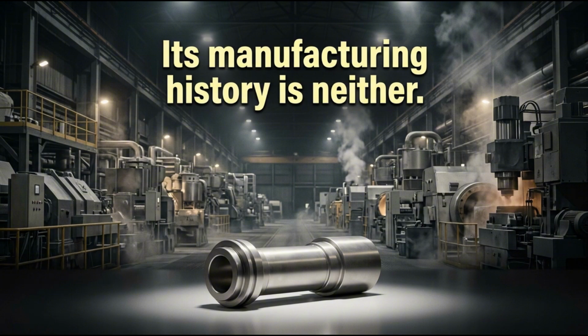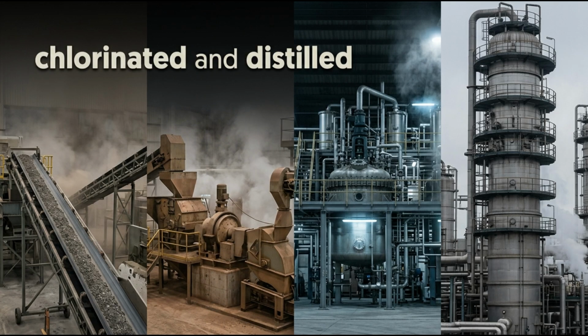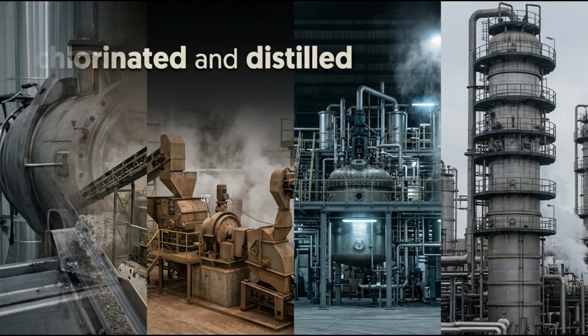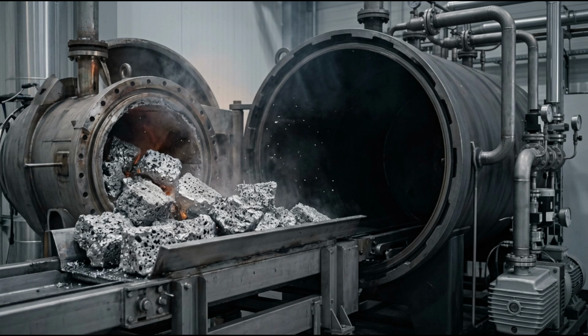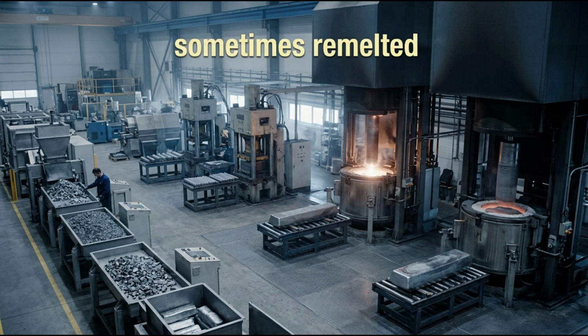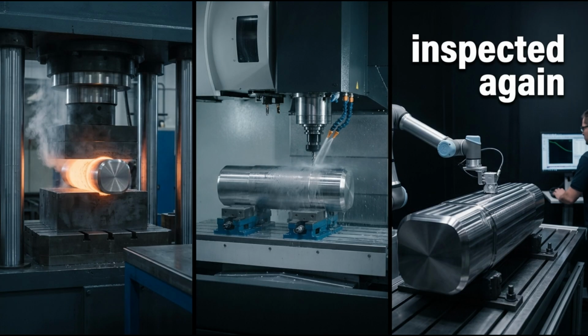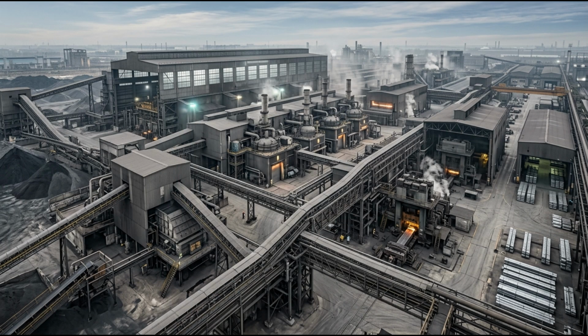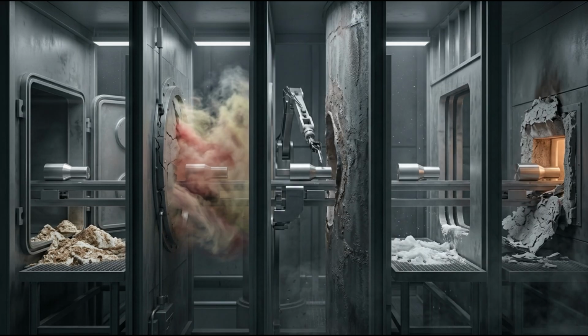First, the mineral is concentrated and upgraded. Then it is chlorinated and distilled. Magnesium frees the titanium, and vacuum removes what remains. The sponge is crushed, inspected, blended, pressed, melted, and sometimes remelted. Then the ingot is forged, machined, and inspected again. Titanium is not expensive because any one of those steps is impossible. It is expensive because nearly every step must protect the metal from the next source of contamination.